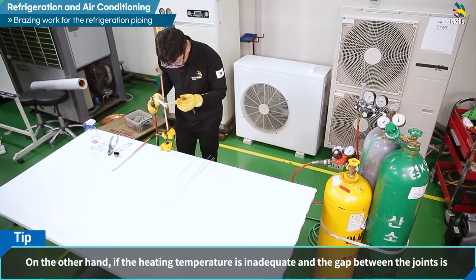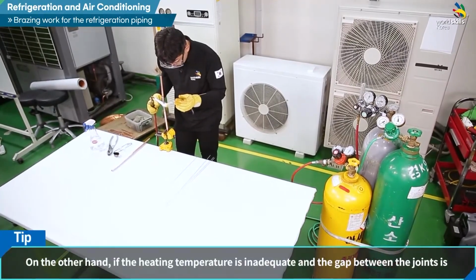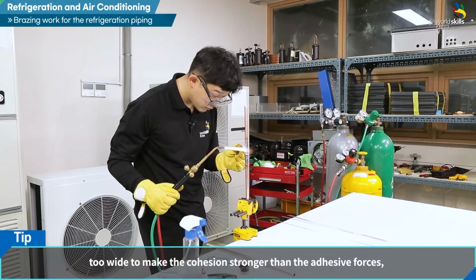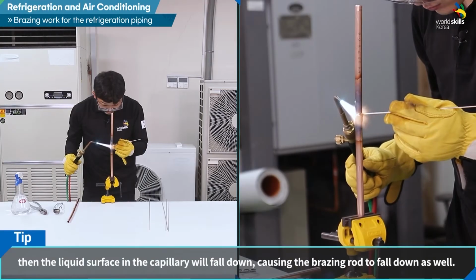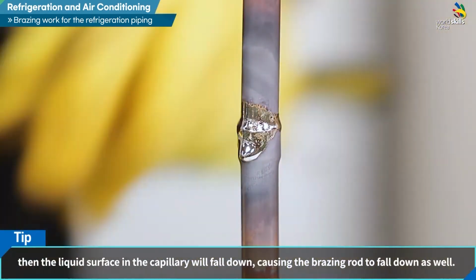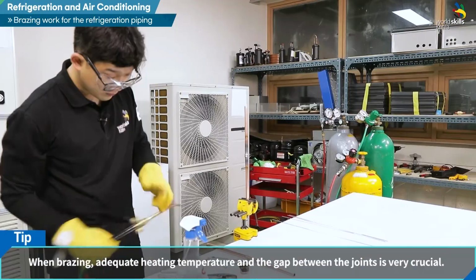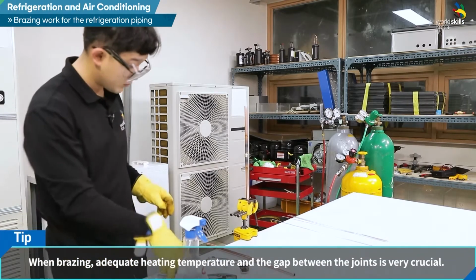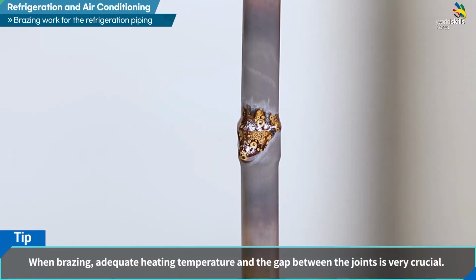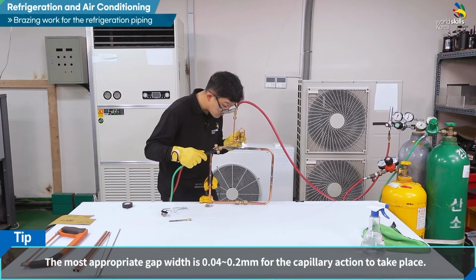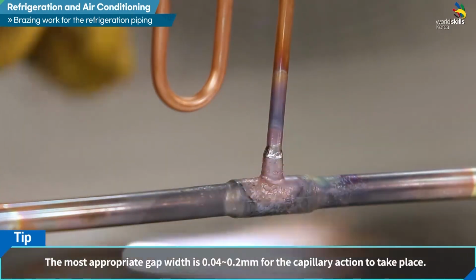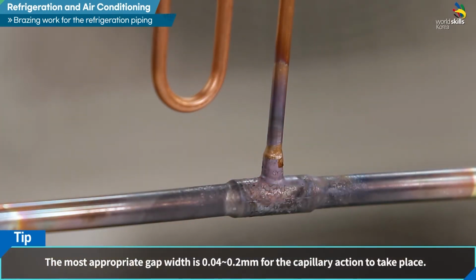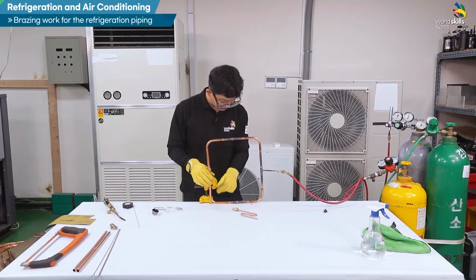On the other hand, if the heating temperature is inadequate and the gap between the joints is too wide to make the cohesion stronger than the adhesive forces, then the liquid surface in the capillary will fall down, causing the brazing rod to fall down as well. Therefore, when brazing, adequate heating temperature and the gap between the joints are very crucial. The most appropriate gap width is 0.04 to 0.2 millimeters for the capillary action to take place.